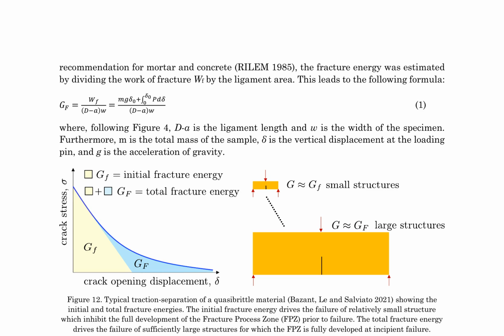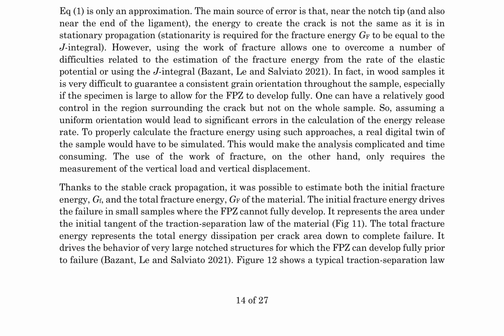The results from the SENB tests show that the thermal modification process significantly affects the fracture energy in both configurations, with a higher initial fracture energy observed in the unmodified specimens compared to the thermally modified ones. However, the total fracture energy is higher in the thermally modified specimens, indicating that the thermal modification process enhances the wood's resistance to cracking in large structures.